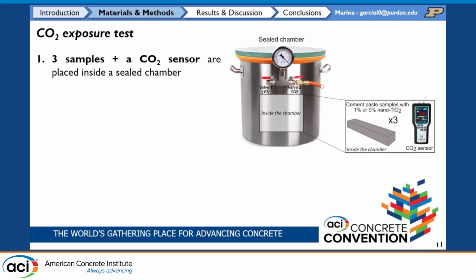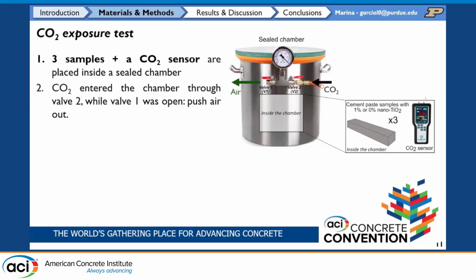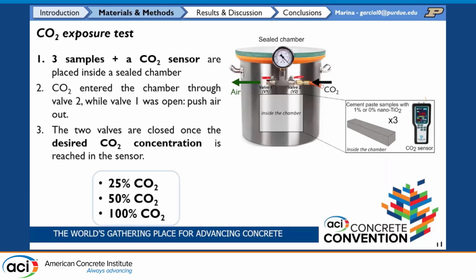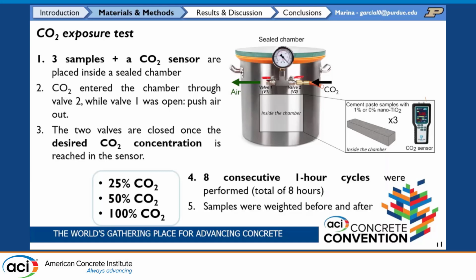The CO2 exposure test that we tested our samples with consisted of, first, placing our samples inside of an enclosed or sealed chamber along with the CO2 sensor. Then we let CO2 enter that enclosed environment, making sure all of the air was being taken out. And then when we reached the desired concentration, we closed both valves and the exposure started. We studied 3 initial CO2 concentrations, which were 25% CO2, 50% CO2, and 100% CO2. And once that was reached, we exposed the samples to 8 consecutive 1-hour cycles. So that means that each hour we would be adding more CO2 until we reached that desired concentration every time.